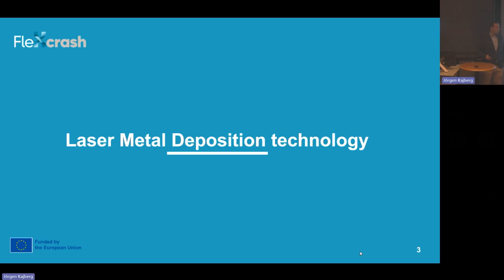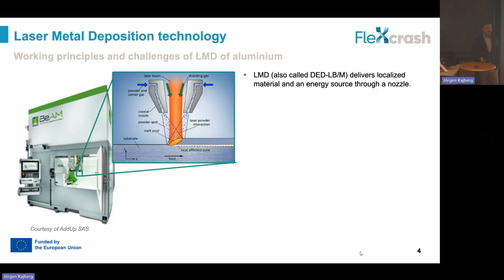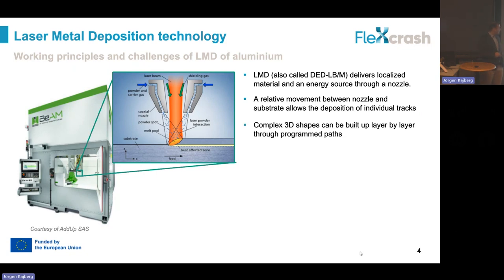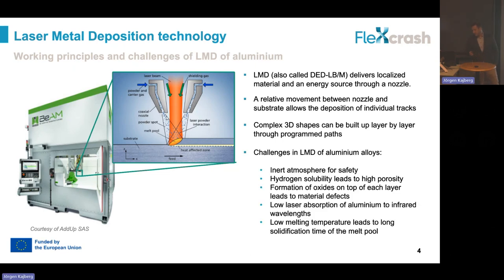So laser metal deposition is an additive manufacturing technology that is also called direct energy deposition with laser beam and metal. And the aim, very similar to plastic 3D printing, is that we have a nozzle through which we deliver energy and material that then combine in a melt pool to add material to this melt pool. With the relative movement between the nozzle and the substrate, we then create tracks with the addition of material. The animation is not working, but we can have these relative movements.